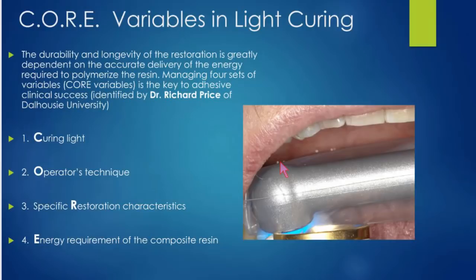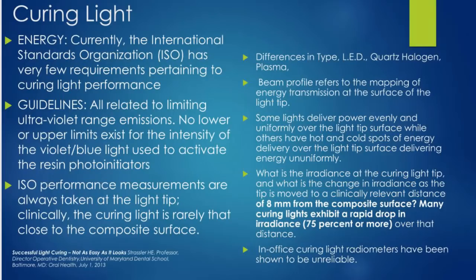So if it says 4 millimeters, that means that they probably allowed for about 5 millimeters away for curing. But if your box is going to be deeper than 4 millimeters, I certainly wouldn't try to build it up all in one bulk fill. So the last thing is, what is the energy requirement of the composite resin, which would have to do with what type of a light, what type of wavelength are we using in the given light system that we have. So I just want you to pay very close attention to what you're doing with your curing light, because very often this is the difference between good and bad photo initiation of the restorative material.